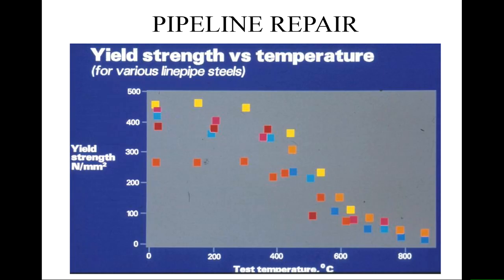The other thing that you need to know when you're considering welding on a pipe containing the gas is that the design stresses that you've used in all your calculations are those stresses and strengths measured at room temperature. And unfortunately, most materials, before they melt, their strengths will start to drop. So if we take a whole set of different steels here, a range of different steels of different strengths at room temperature, going from something around here, this is something like X42 up to X50, 55, something like that. You'll see that up to about 300 degrees C, there's not a lot of change in strength in these cases, but for all of the steels, regardless of grade, the strength drops.